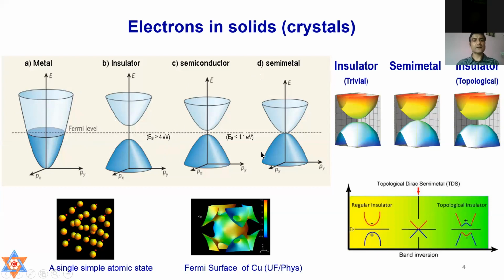So what we try to understand from here is the band structure, for those who are doing DFT calculations. The bands are going from the valence region, which is below the Fermi level, to the conduction region, and they are crossing the Fermi level without any sort of gap. So this indicates that the material is a metal.